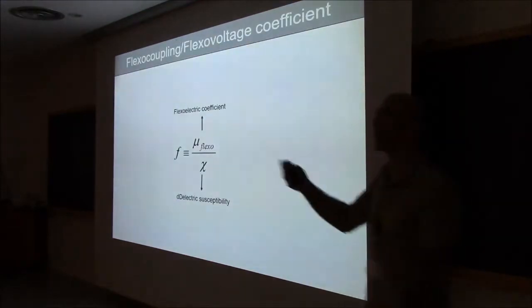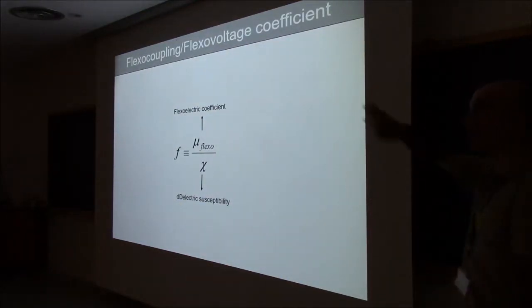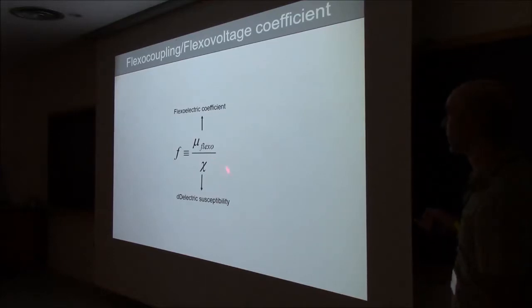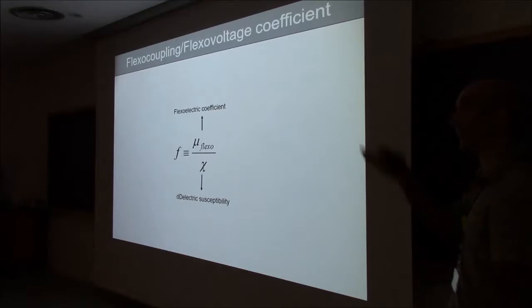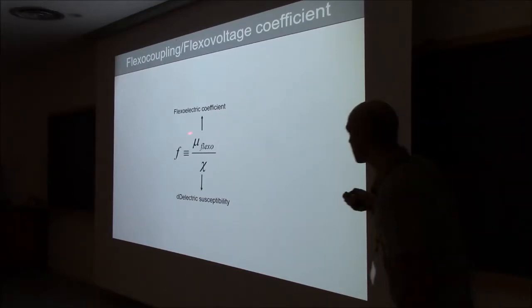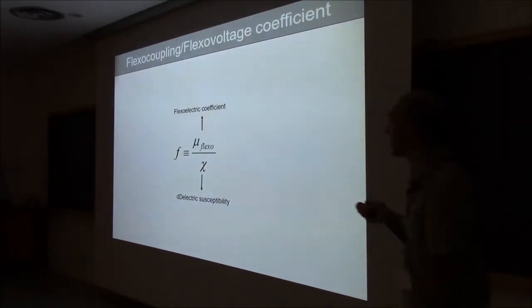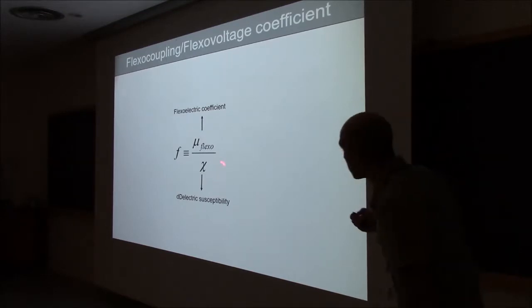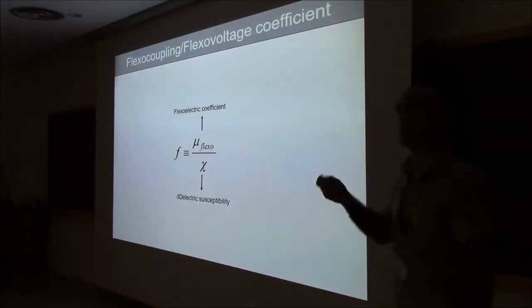So the first thing to do a proper comparison is to get rid of the temperature dependence, and we do so by dividing over the dielectric susceptibility. And that's the F coefficient that you asked about before. So this is the flexoelectric coefficient that you measure experimentally. This is the same thing divided by the dielectric constant. We get F. Okay? We call that F.